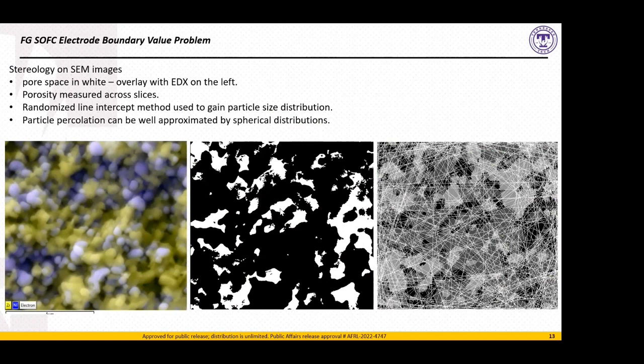After this, we pull out the porosity. We threshold the porosity locally, and then we use a randomized line intercept method to discern, again, the particle size distributions after the cells have been sintered and prepared for operation. Noticing here again, quickly in the image on the left-hand side, going forward within our analysis, we're going to assume that all of the grains have approximately a spherical structure to them, which does well. But the theory that we'll lay out is not necessarily unique to spherical distributions. It can also be applied to other morphology particles as well.